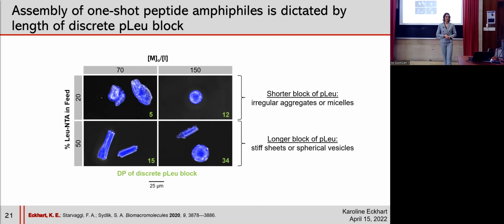And then when we increase the length of that discrete polyleucine block, we either get stiff sheets or more spherical vesicle type structures. So overall, this work contributes by coming up with a more convenient way to access a functional copolypeptide amphiphile by using a one-shot polymerization. And this could be a more accessible technique for interdisciplinary labs that might not have ready access to an NMR or an FTIR, where they can actually check conversion of that first block to make sure that it's been completed.